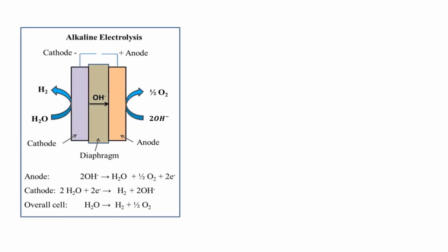In this kind of system, we have two different electrodes, anode and cathode. And if we were to do the electrolysis in alkaline solution, at the anode side, we can take hydroxyl ions and convert them into oxygen and electrons, where the electrons can then travel to the cathode side and reduce water to hydrogen gas. But the problem is the oxygen evolution reaction side, where the reaction is typically slower.